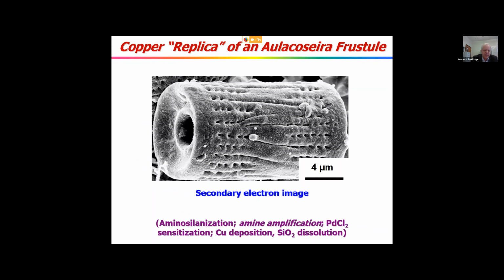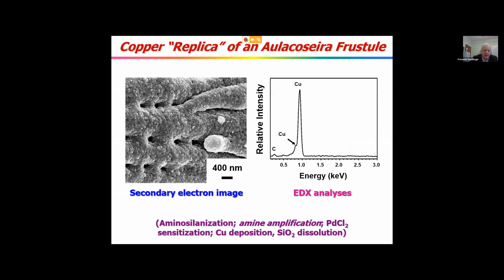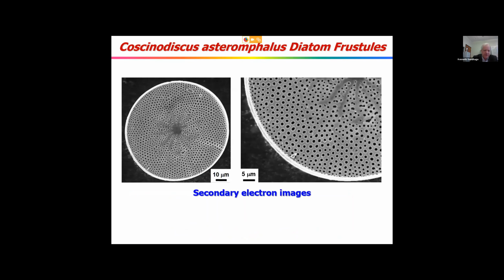So here, in fact, is a copper replica. The silica has already been dissolved away through pinholes occasionally in the coating, and you can see you get a very nice replica, negative replica of the diatom. This shows EDX that there is no more silica left going through the coating. We've done this also with Coscinodiscus asteromphalus for a particular optical application I'll mention quickly here.